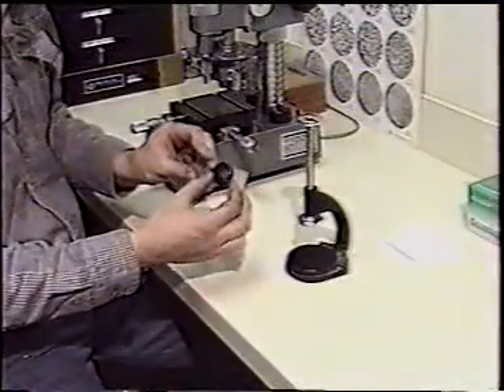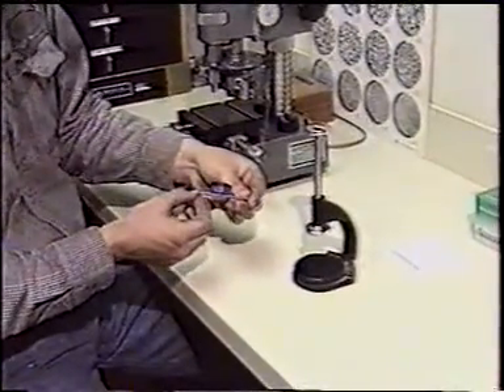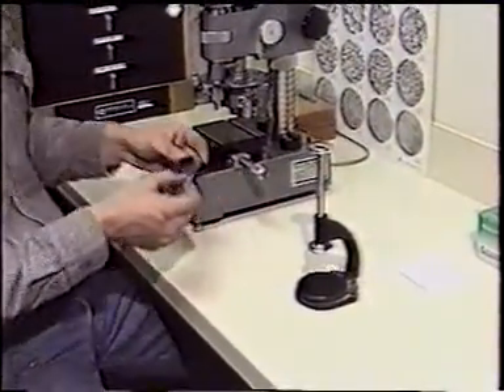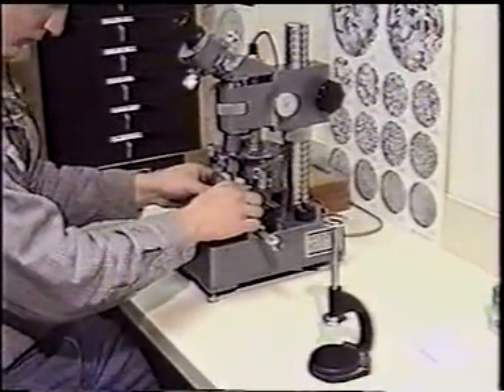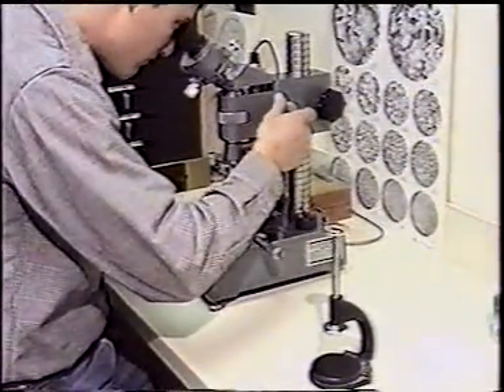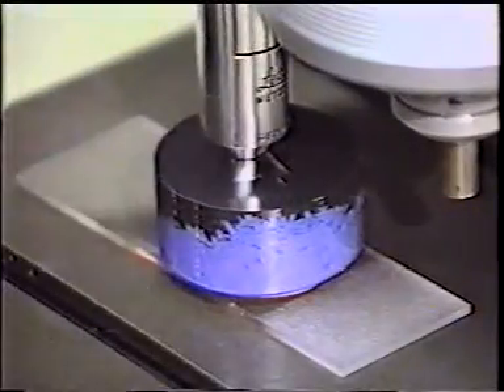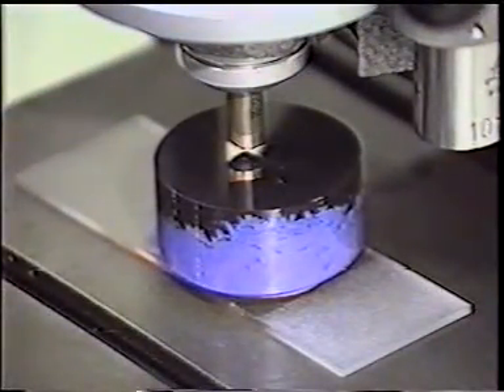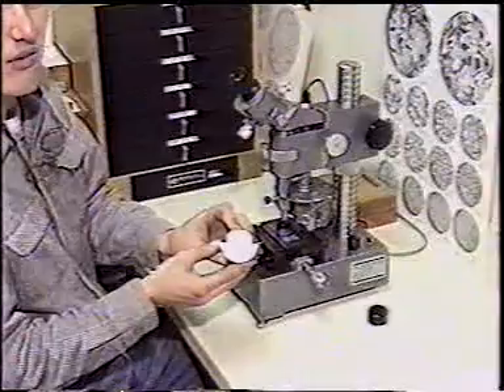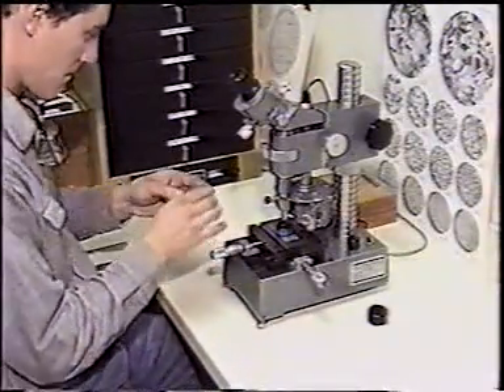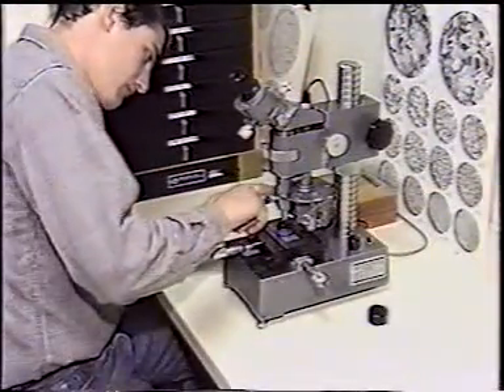Macroscopic and microscopic hardness testing indicate the resistance of a material to abrasive wear. Harder materials are likely to cut or scratch softer materials, so comparative hardness of two sliding surfaces may be important. Micro-hardness measurements on martensitic steels may indicate that frictional heat has over-tempered the steel. When used in conjunction with a tempering curve, plotting hardness to tempering temperature, the micro-hardness measurements can allow a rough estimate of surface temperature. Hardness measurements can also indicate whether or not a worn part was heat-treated correctly.